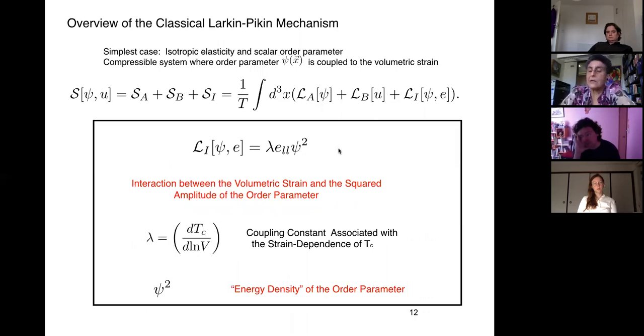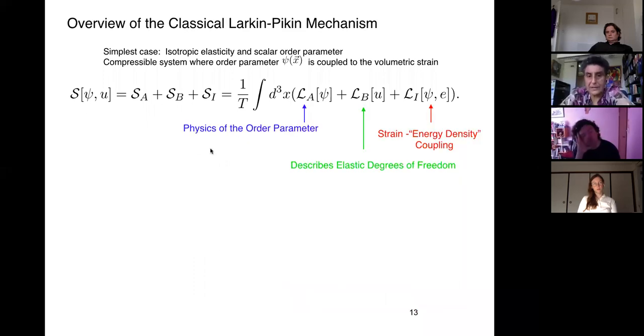Now we have this Larkin-Pikin interaction. This is the interaction between the volumetric strain and the squared amplitude of the order parameter, and lambda is the coupling constant associated with the strain dependence of T_C. Now, we can think of psi squared as the energy density of the order parameter, so in this sense, this is a strain energy density coupling. So this is what we have: an action with the physics of the order parameter, elastic degrees of freedom, and strain energy density coupling.